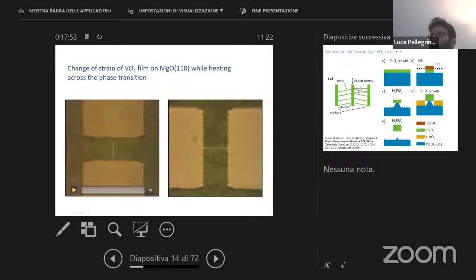As you can see here, we are heating the sample in one direction. You see here that it is changing the shape. Even the freestanding regions are here. So you see, and the bend is changing. And here, the opposite behavior. You are heating up the system. This will stress, will strain, and this will compress. And even the bridge will compress. You see, again, I will show you again. The bridge is under tensile strain, and then you have compression, so the bridge is bending. This video is made during the heating of the system across the phase transition.